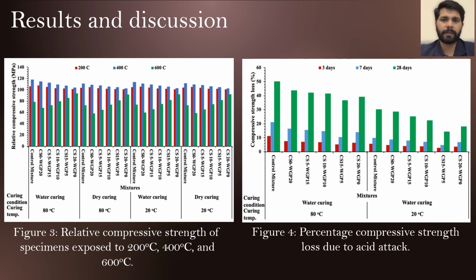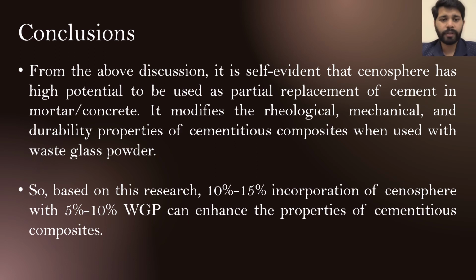Finally, the conclusions from the above discussion, it can be suggested that Cenosphere has a high potential to be used as a supplementary cementitious material and a partial replacement of cement in concrete and mortar. It modifies the rheological, mechanical, and durability properties of cementitious composite when used in combination with waste glass. That will definitely promote the sustainable built environment. So based on the current research, it can be concluded that 10 to 15% incorporation of Cenosphere with 5 to 10% replacement of waste glass powder can enhance the properties of cementitious composites.